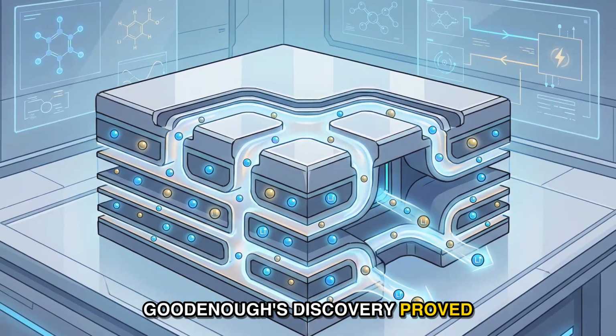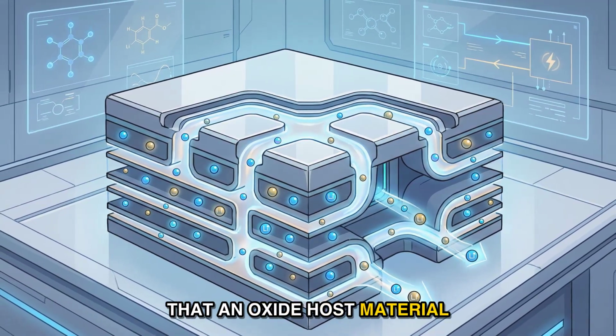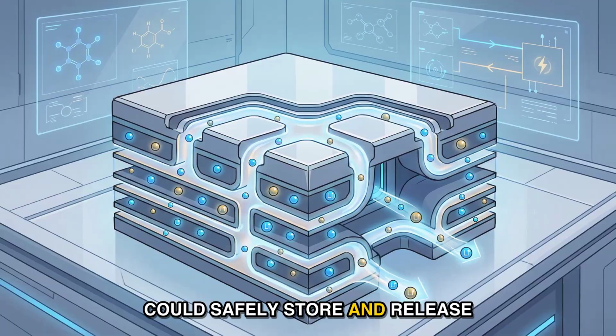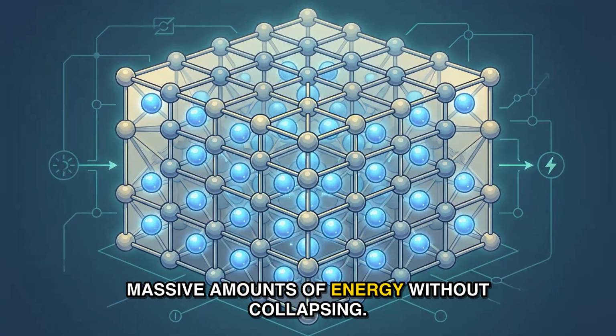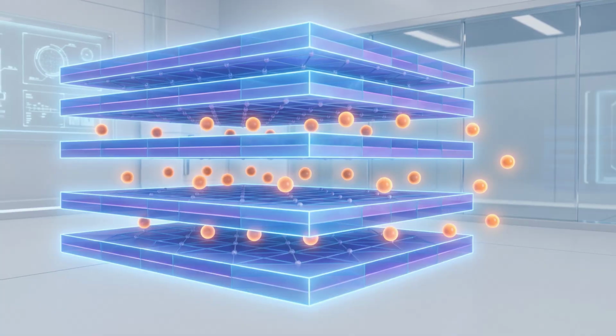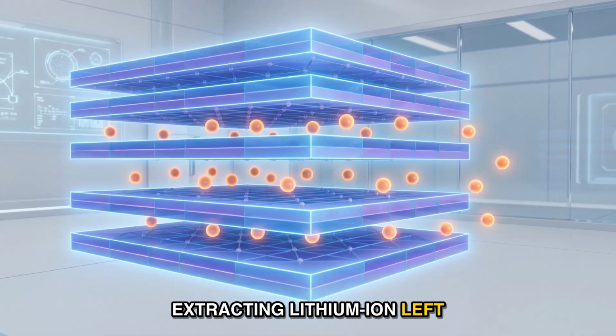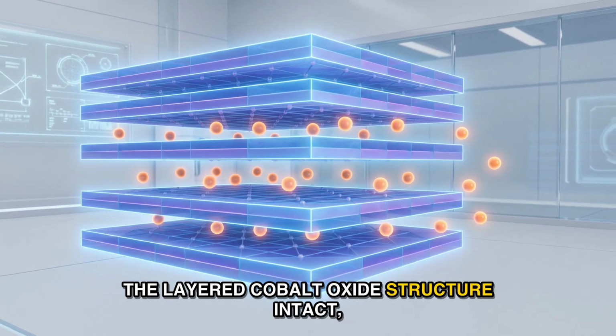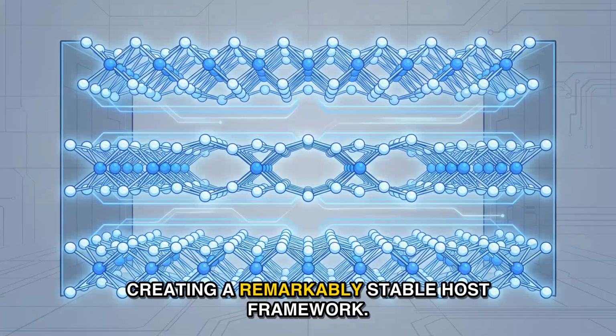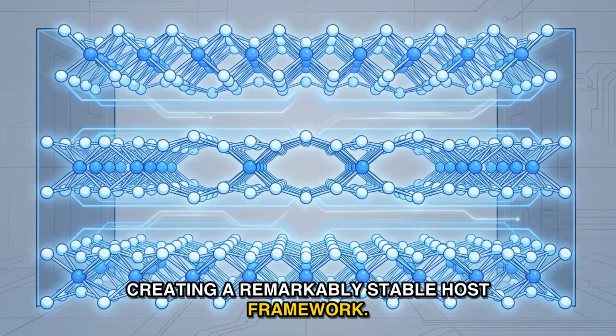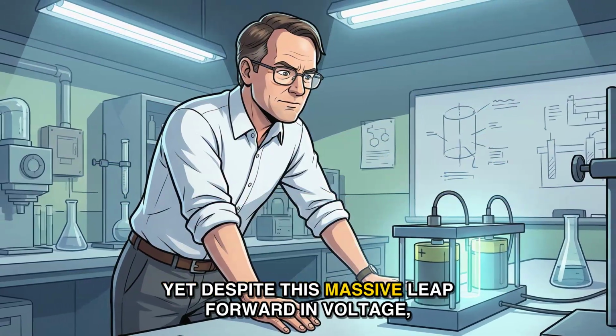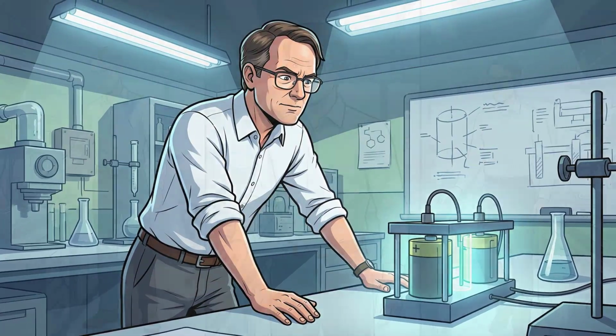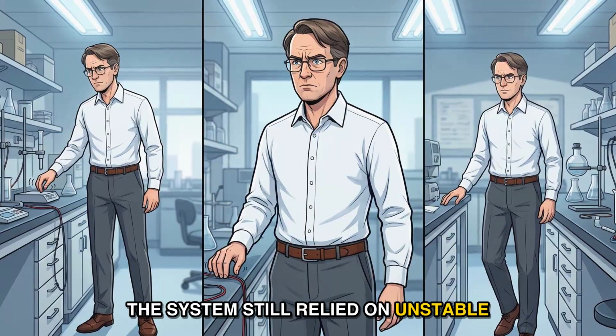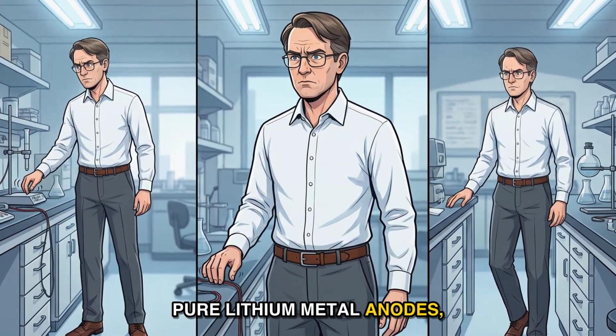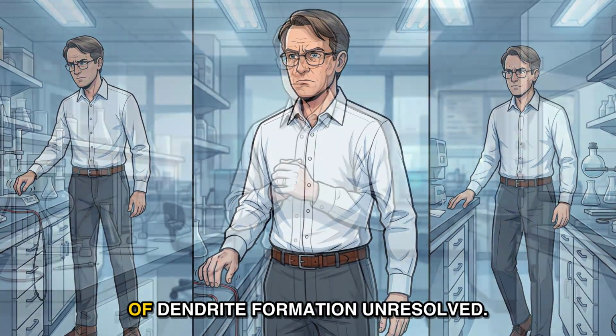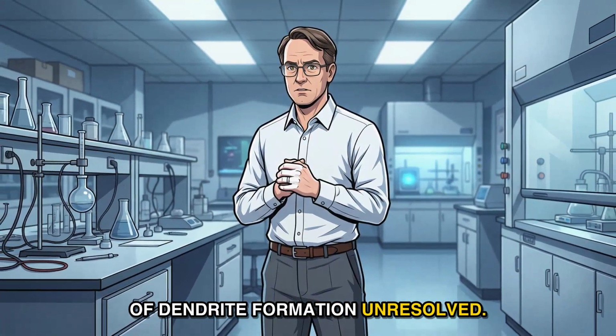Goodenough's discovery proved that an oxide host material could safely store and release massive amounts of energy without collapsing. Extracting lithium ions left the layered cobalt oxide structure intact, creating a remarkably stable host framework. Yet despite this massive leap forward in voltage, the system still relied on unstable pure lithium metal anodes, leaving the severe risk of dendrite formation unresolved.